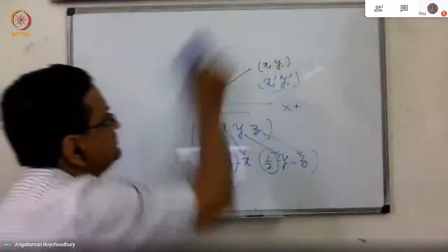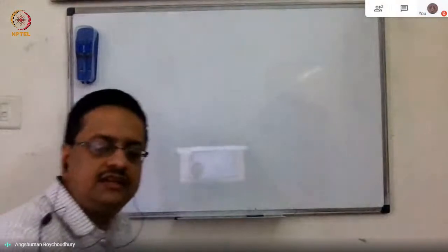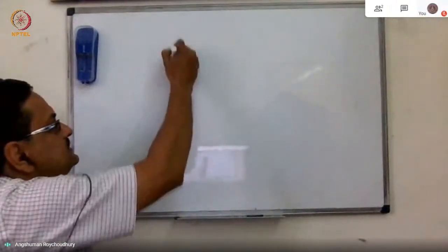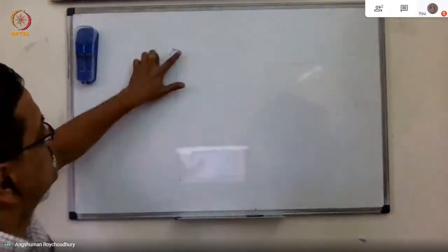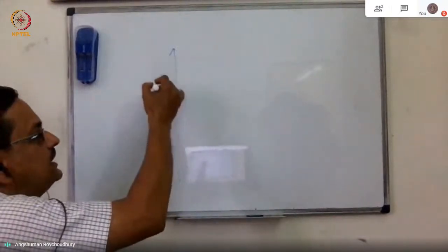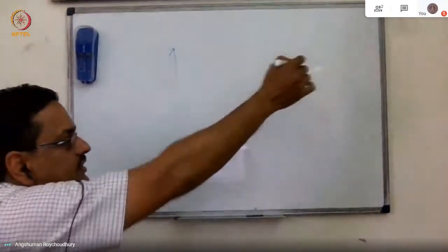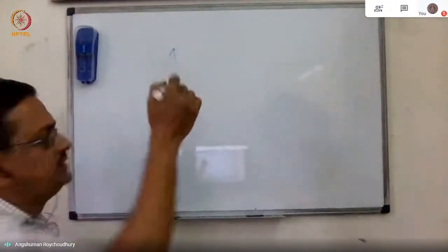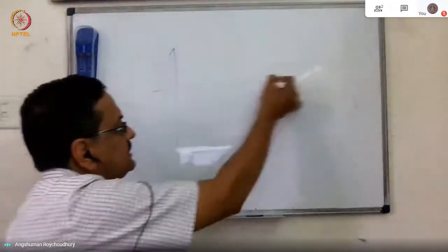This you may visualize in case of the space group P212121, where you may have noticed that the 2-1 screw axis that we considered, if we consider one 2-1 screw axis in the plane of the board like that, then we consider a second 2-1 screw which is 1/4 shifted from the plane of the board somewhere here.